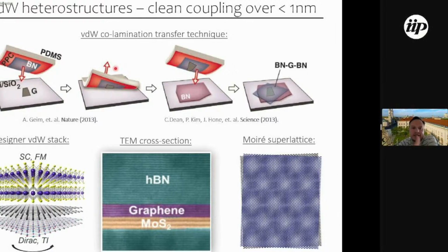So we can exfoliate any single layer of a van der Waals material that we want. Often this is graphene or hBN that we use for the assembly of these devices. We have also developed over the years this co-lamination transfer technique, which allows us to assemble these layers one on top of one another. This allows us to choose any sequence of material species that we like: insulators, metals, superconductors, ferromagnets, Dirac materials, topological insulators, you name it. Any material from the library of quantum phenomena, you can assemble with one another like that.